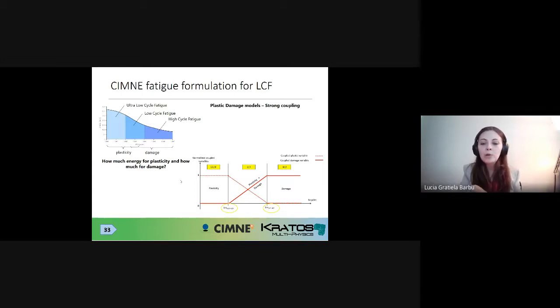But what happens when you are interested in migrating, for instance, from low cycle fatigue to high cycle fatigue? You had some plasticity at the beginning, but then you are going towards a load history which only needs to give damage behavior inside your model. Well, if you're using a weakly coupled model, you won't be able to do this, because if you stop plasticity, automatically this stops damage. So this is why we needed strong coupling, why we needed to integrate damage and plasticity at the same time, and we needed models which would be easily reduced to each one of the base phenomena, either reduced to plasticity, or reduced to damage if needed.